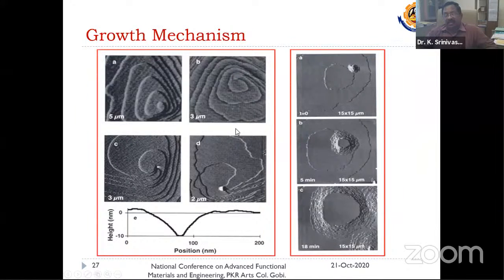Of course, nowadays there are techniques available with which one can see the mechanism behind any crystal growth process. So this mechanism is known as the screw dislocation mechanism. In a crystal, the screw dislocation helps to grow single crystals along a particular direction. You know the dislocations, edge dislocation, screw dislocation, etc., are possible in a single crystal. So if there is a screw dislocation, the Burgers vector and the dislocation directions play a major role here. See, here there is a smaller size nucleation, the cluster of molecules. It is known as two-dimensional nucleation.